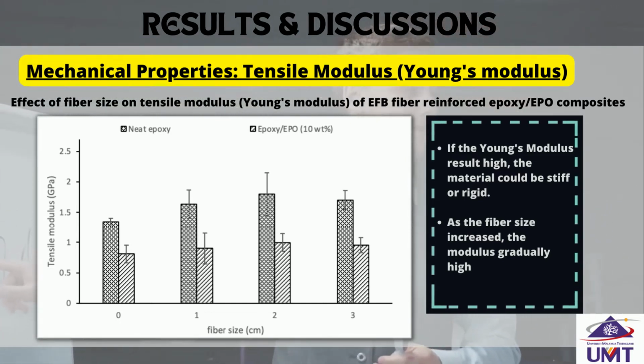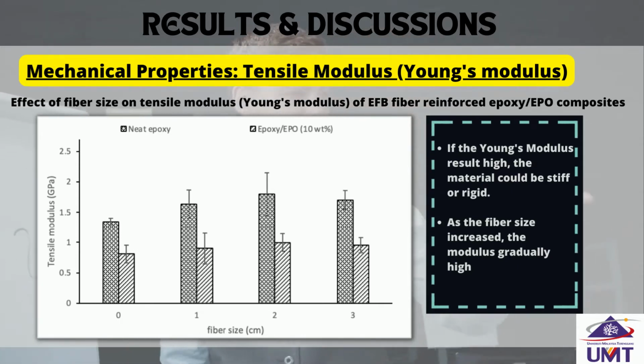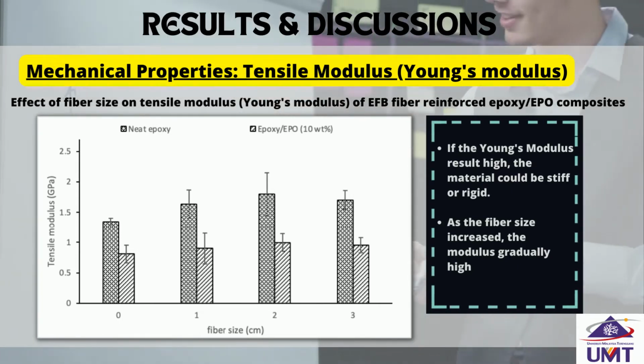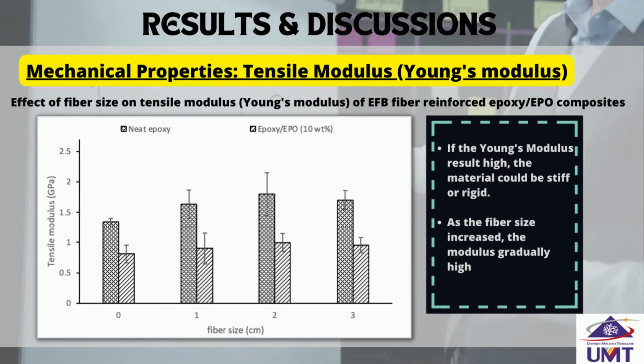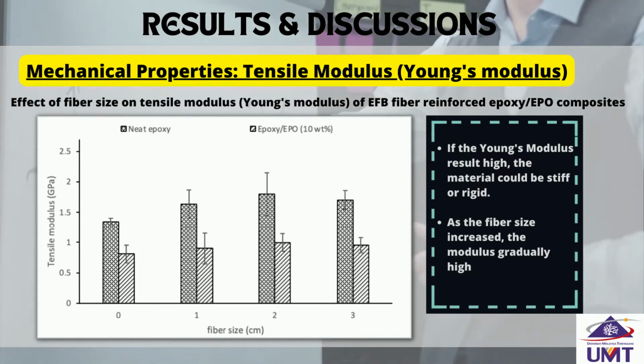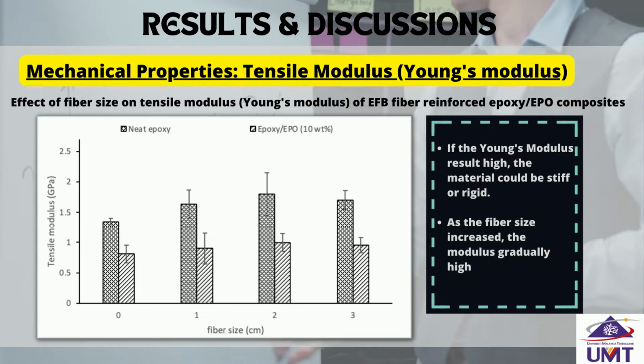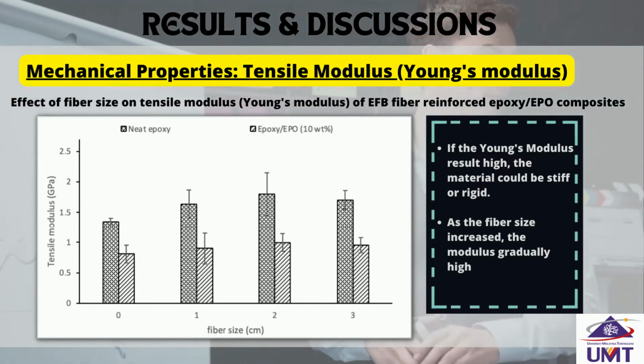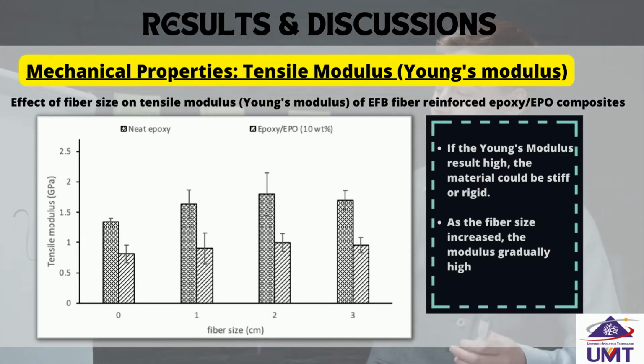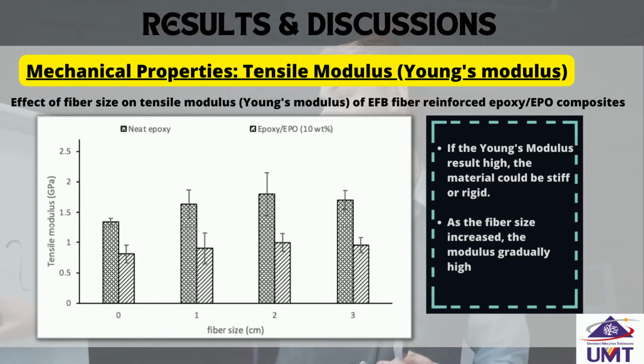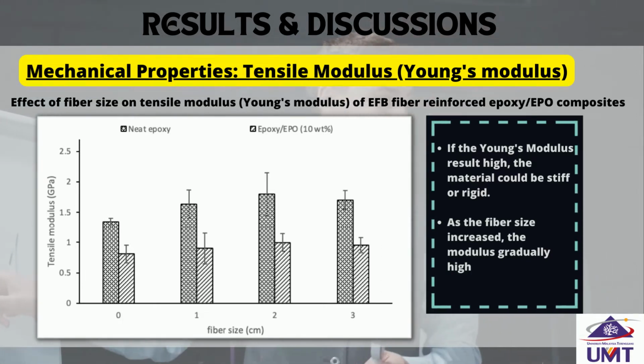Based on the theory from the previous study, as the fiber size increased, the modulus also gradually increased because the fibers are stiffer than the matrix. Based on the tensile modulus result in this study, the fiber size of 2 cm is the most rigid for both neat epoxy composites and epoxy EPO composites.